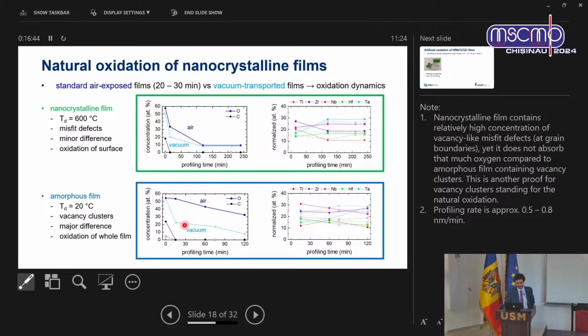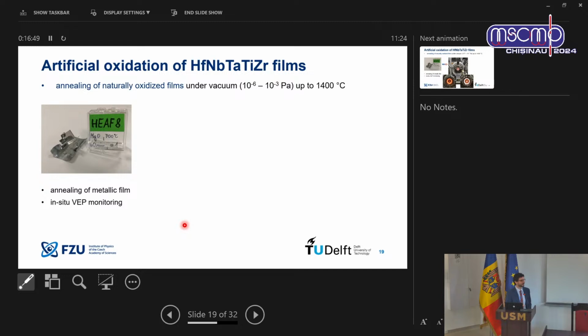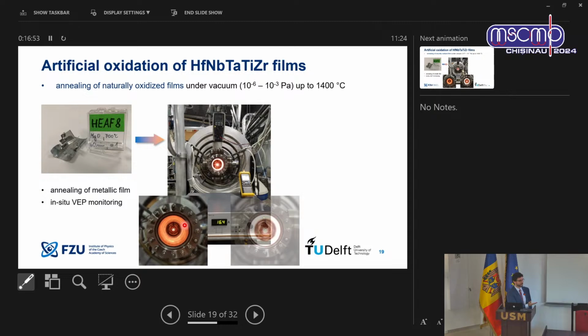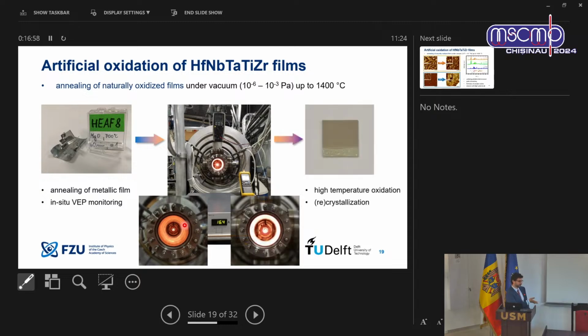I guess so. Also, we still had in mind to transform our films into the high entropy phase. And since we couldn't increase the temperature during the deposition, we tried to do it after it. And we believe that since this natural oxidation is relatively weak, we can achieve it. So we put it into a vacuum chamber. Actually, it was the apparatus for measurement of positron annihilation spectroscopy, and heated it up step by step up to the temperatures of 1,400 degrees.